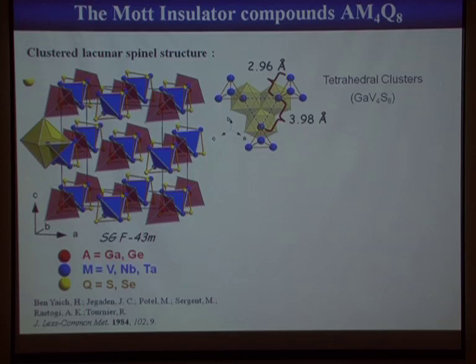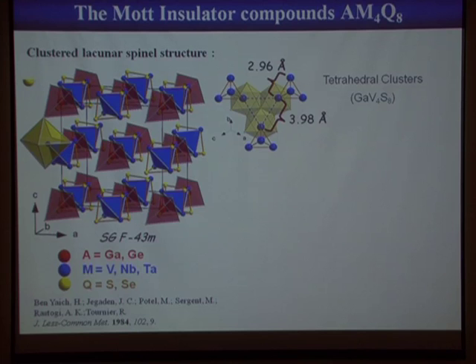These compounds have a very nice lacunar spinel structure with a notable feature: tetrahedral transition metal clusters. The distances within these clusters are very short — less than 3 Ångströms — meaning you have metal-metal bonding. Between clusters, the distance is very large, about 4 Ångströms, which prevents inter-cluster metal-metal bonding. This has a strong impact on the electronic structure.